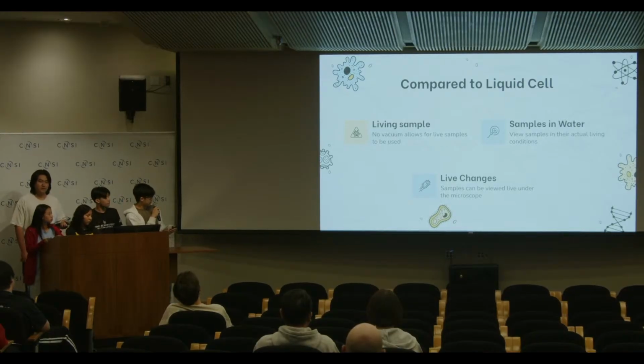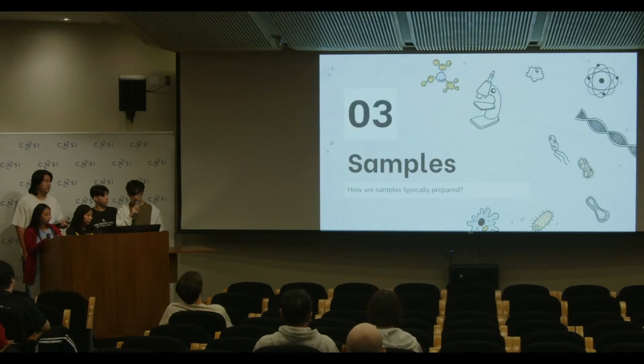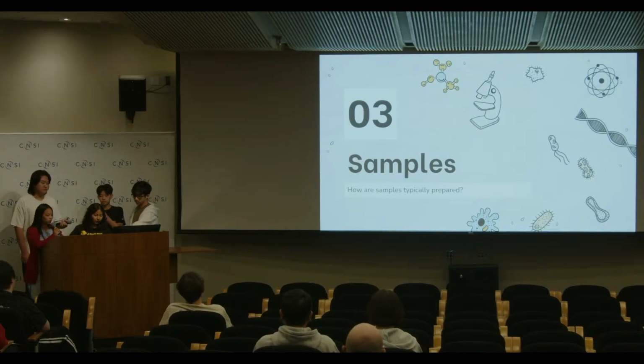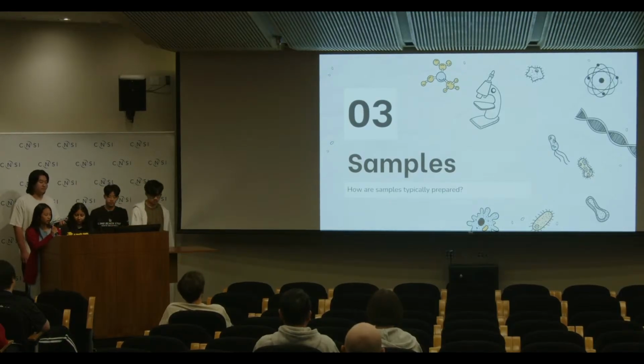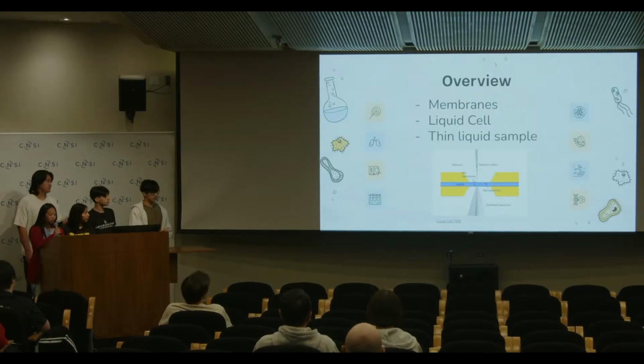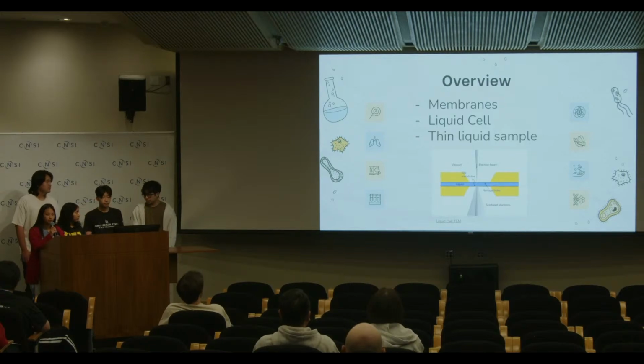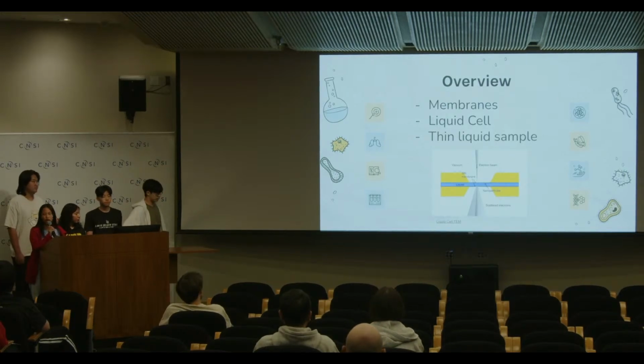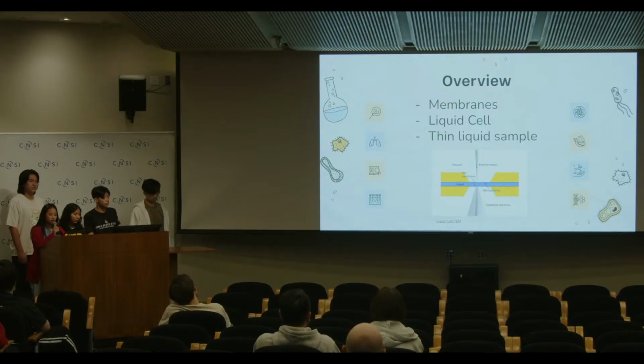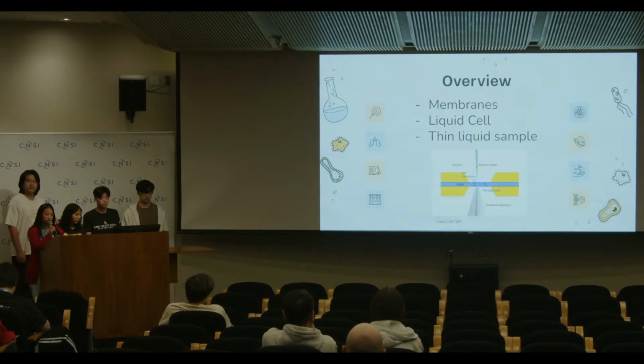And so moving on, we'll go into how to prepare the sample. So I will talk about how samples are typically prepared. Liquid samples are placed in a small space between two thin, tough, and high transmittance membranes to create a sealed liquid cell. The cell contains the wet sample in a solution environment while still allowing the electron beam to pass through for imaging. So the sample has to be thin for the electron beam to penetrate and achieve optimal imaging conditions.